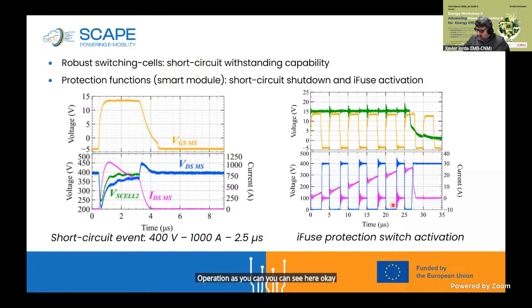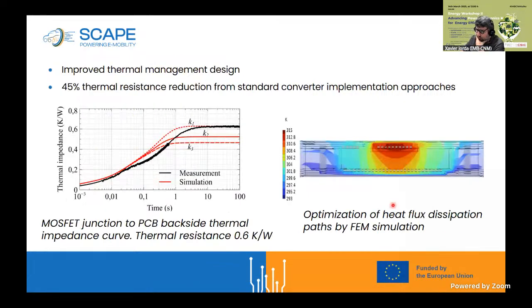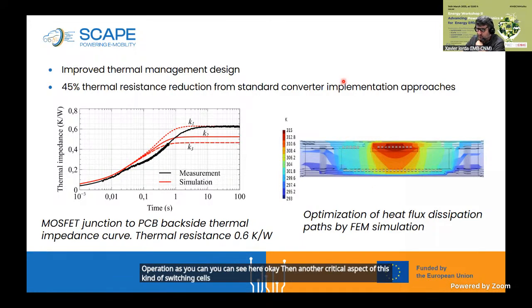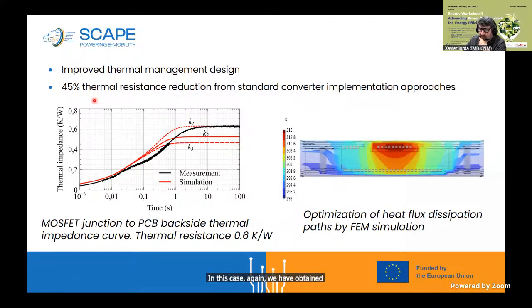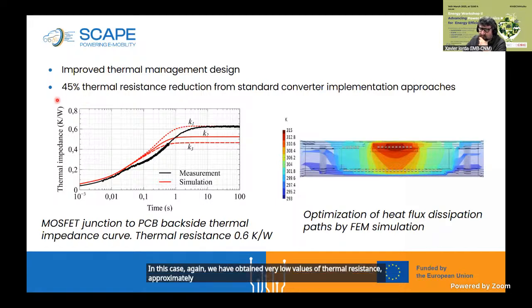Okay. Then another critical aspect of this kind of switching cells is their thermal behavior, the capability for dissipating the heat generated under operation. In this case, again, we have obtained very low values of thermal resistance, approximately 45% below standard values from commercial and conventional solutions. This you can see here